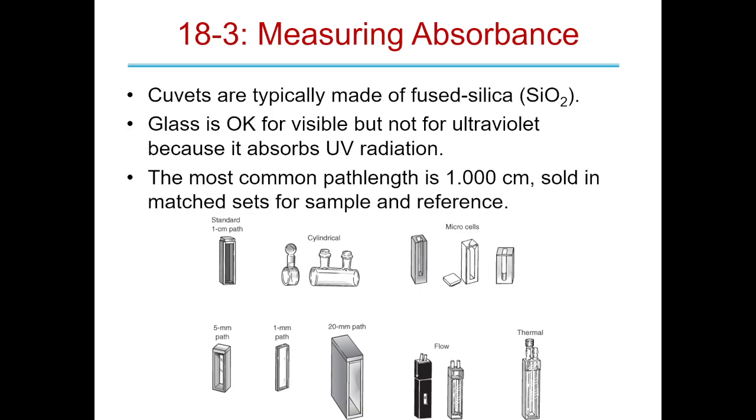However, can you get a suntan sitting in front of the window? This window or any window. No. Glass absorbs UV radiation, right? So any double pane window will absorb 90-something percent of the UV radiation. Okay? And so no, you can't get a suntan or sunburn sitting in front of a window. You also can't take UV spectra with a glass cuvette because you'll lose almost all your UV radiation, right? It also causes it to heat up and re-radiate, by the way, which is a whole other series of problems.